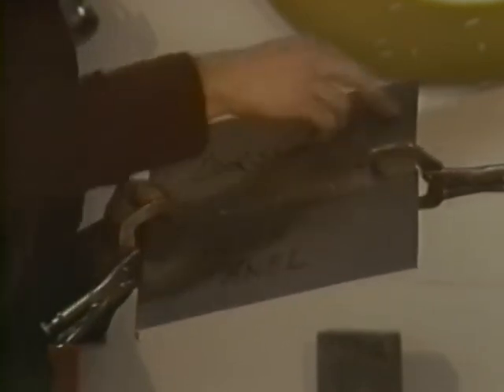Now, if you've got a panel spot welder, you could also spot weld them instead of MIG welding them. Another method that you could use is by plug brazing the holes, but you can get a lot of warpage up in here. You got to make sure that you cool the weld with compressed air. You don't use water because water will get trapped up in here and start rusting.